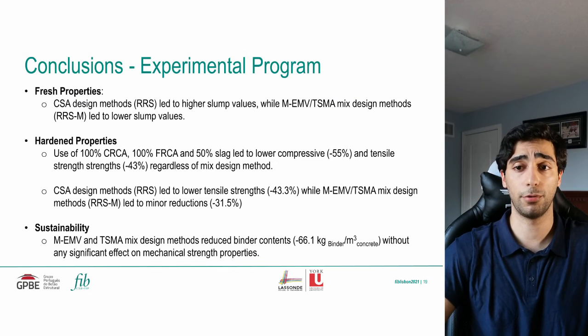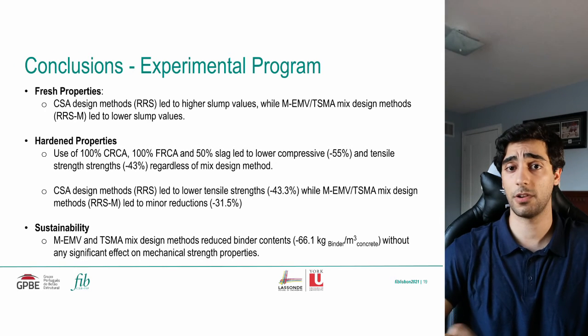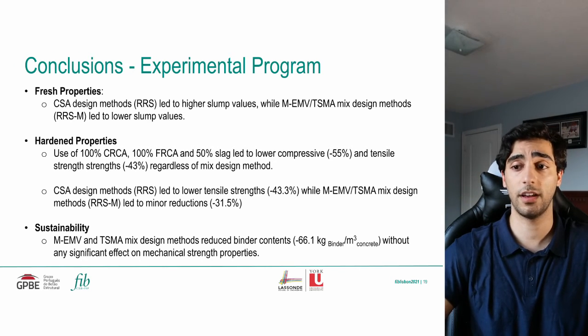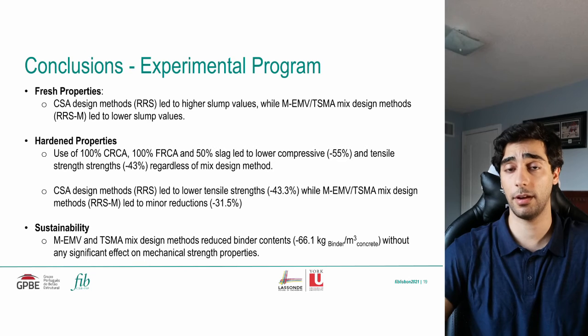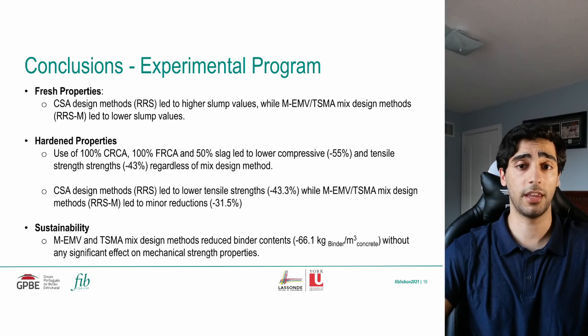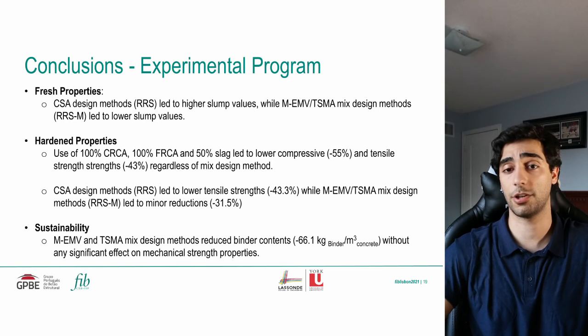To sum up the experimental program, in terms of fresh properties, the CSA design mixes led to higher slump values, while the EMV and two-stage mixing approach mix design methods led to lower slump values. In terms of hardened concrete properties, the use of 100% coarse, 100% fine, and 50% slag led to lower compressive strength values, up to 55% lower, and tensile strength reductions up to 43%, regardless of the mixture design method. It should be noted that the CSA mix design methods led to lower tensile strength, with reductions up to 43.3%, while the use of the EMV and two-stage mixing approach led to minor reductions, with only 31.5% reduction observed.